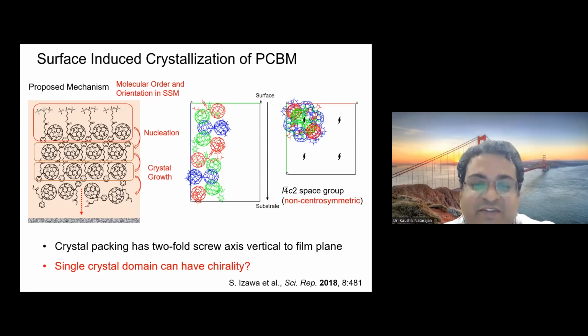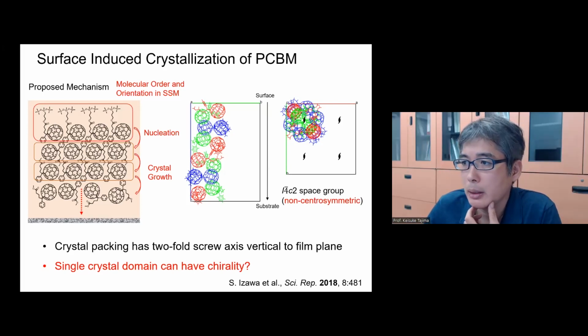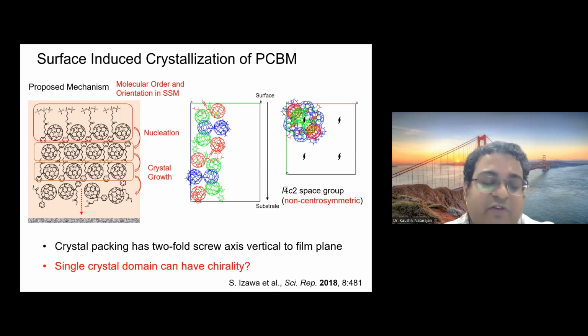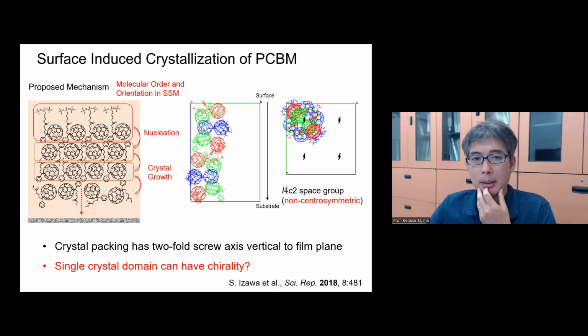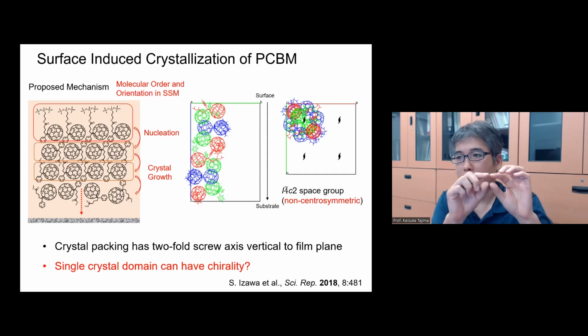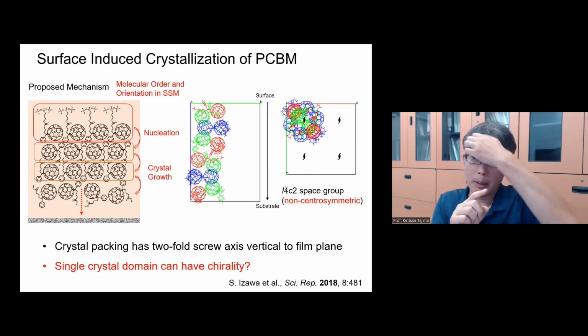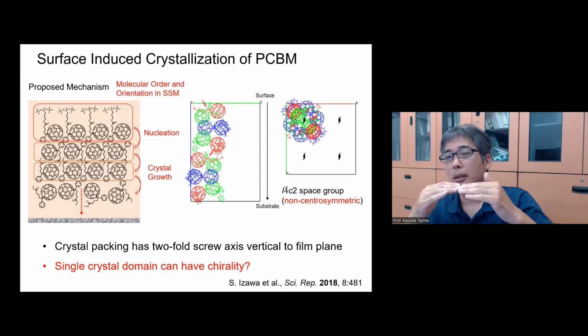Thank you, Professor. The next question is, have you observed any relationship between the degree of crystallinity and the degree of orientation or tilt angles or anything like that? Degree of crystallinity and degree of orientation in the solar cell? Yeah, in the solar cell or even when surface-induced crystallization occurs. Well, I would say the orientation of the molecule at the surface is not related to the crystallinity of the film in the bulk, because it's already determined by the drying process, right? So the orientation of the molecules on the surface probably doesn't change much even after thermal annealing. But the orientation in the bulk can be affected by crystallization.